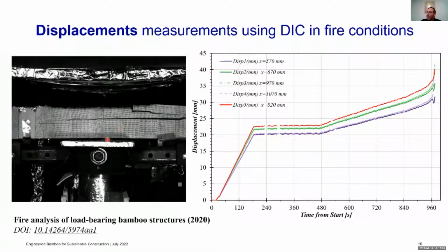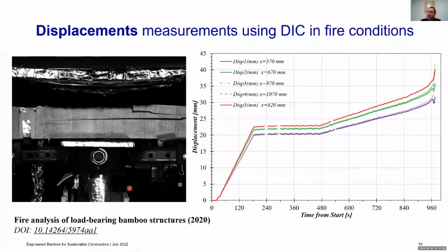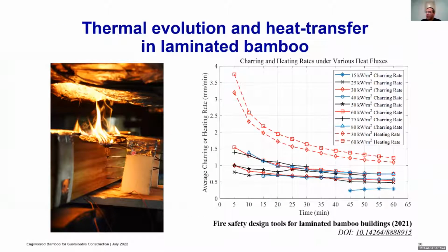We measure deflections and strain with that method, but we also use contact sensors to do that. We use string pots and we use strain gauges. The problem is that the strain gauges were lost very quickly. So with that test and also other tests developed by Ian, we calculated charring rates.